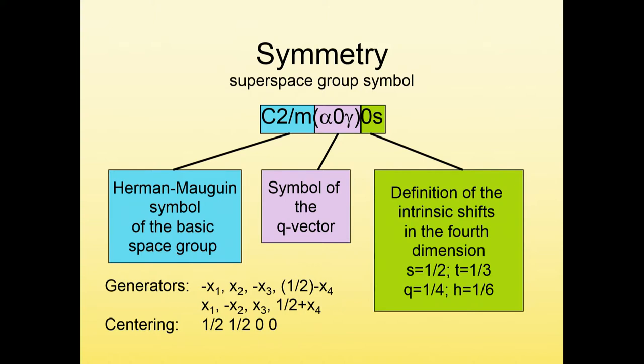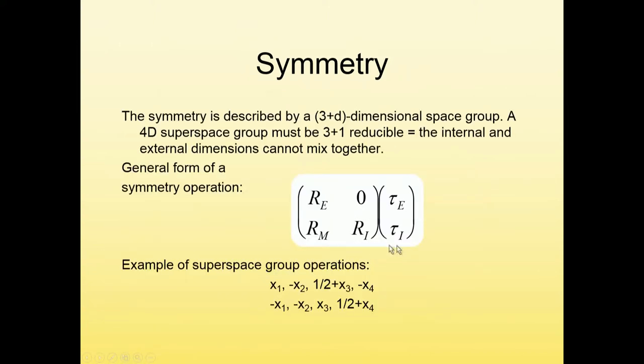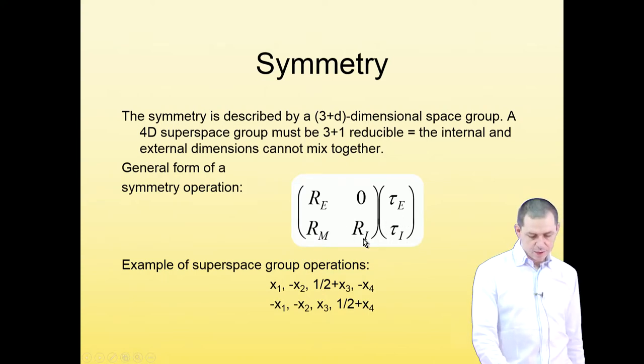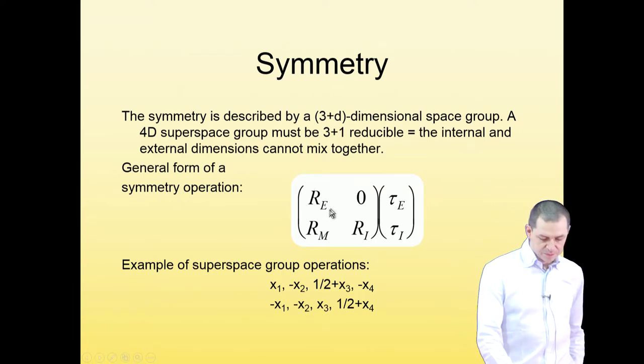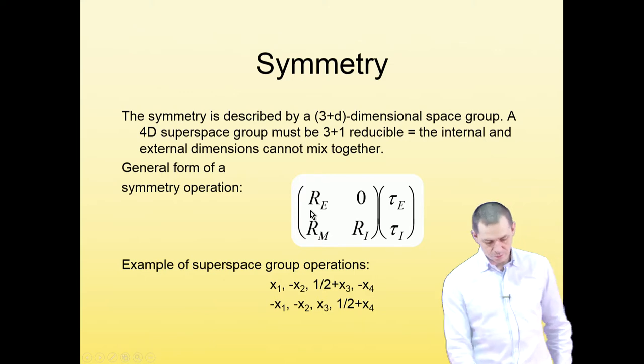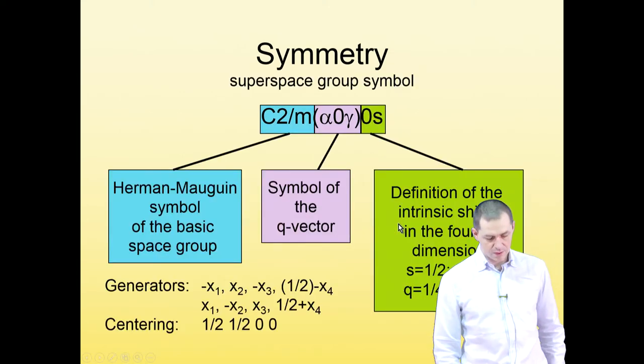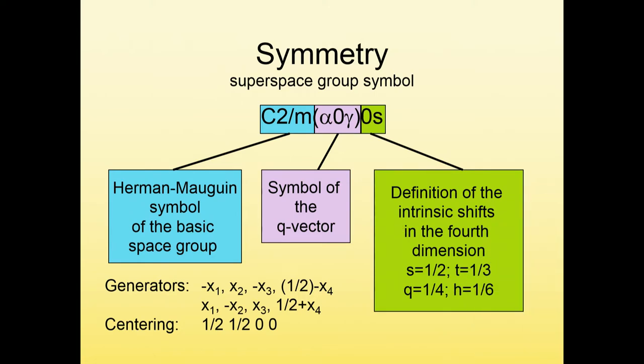And the last part gives the definition of intrinsic shifts in the fourth dimension. So this is the part that is needed to complete the symmetry operator, this part here. This part is defined by the basic space group and the definition of the modulation vector, but this part not, and that needs to be given explicitly in the space group symbol. The letters S mean shift by 1/2, T shift by 1/3, Q shift by 1/4, and H shift by 1/6. So that's all you need, and mostly what you are interested in, at least at first glance, are these two parts. So what is the average symmetry and what is the direction of the modulation vector in the structure.